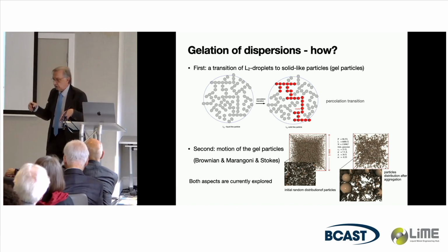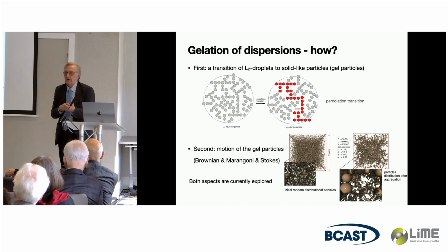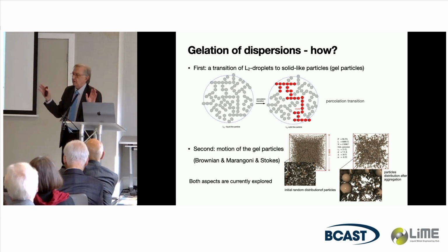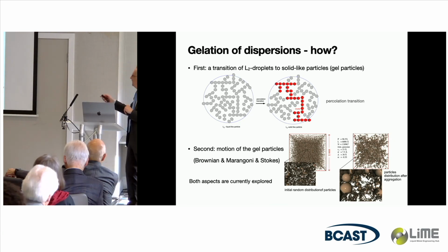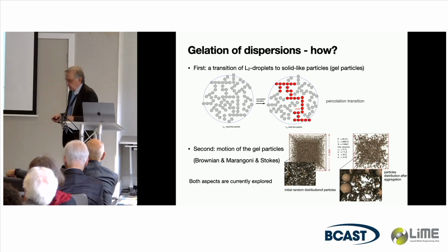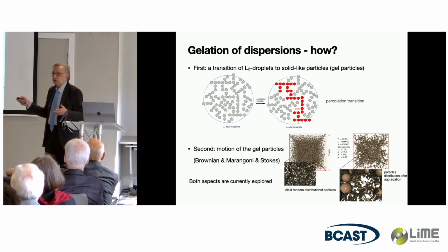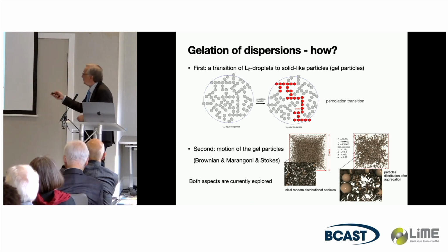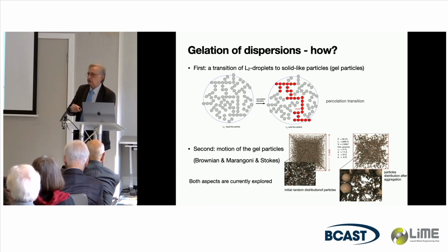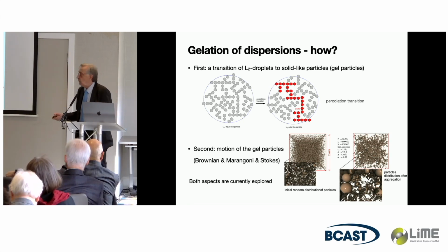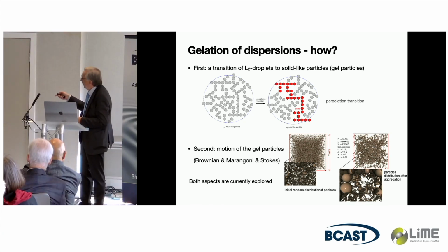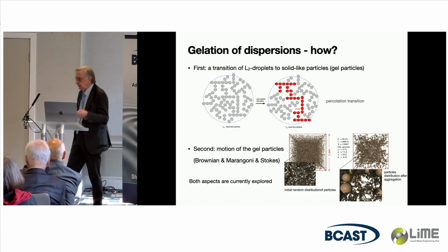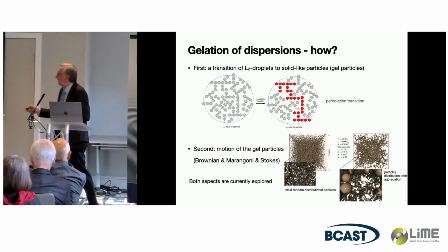If you look into the literature on percolation, look to the book of Aharoni and Stauffer, or there are wonderful websites on percolation available, it says always that beyond a volume fraction of polymers here larger than 40-50%, they will directly make a percolation transition, and then this is a wet gel particle, no longer liquid, not really solid. It's a mixture between liquid and solid, and of course, because it's also liquid, there are oligomers or even monomers therein, so interfacial tension-driven flow would be possible. And so this would then have the ability to connect to each other and make a string-of-pearls network and a spreading cluster.